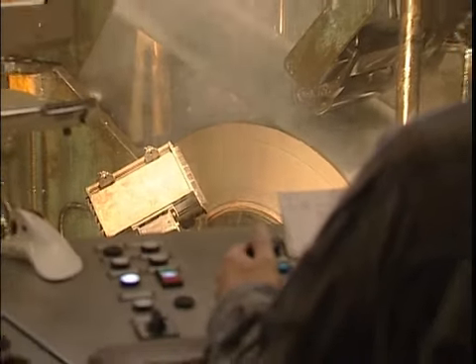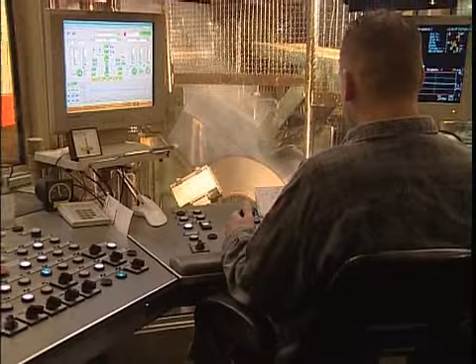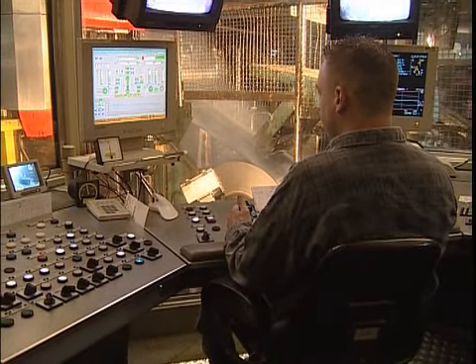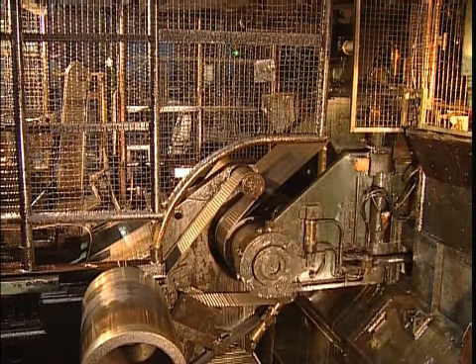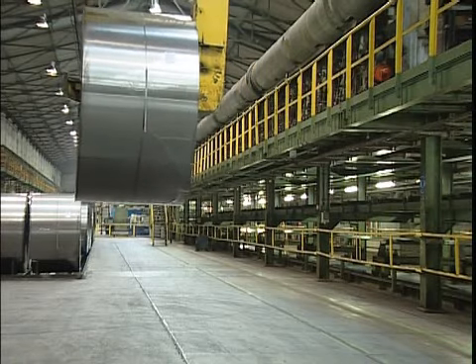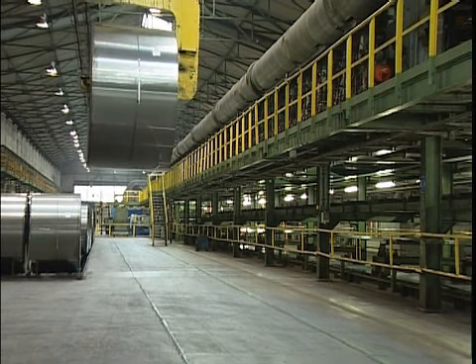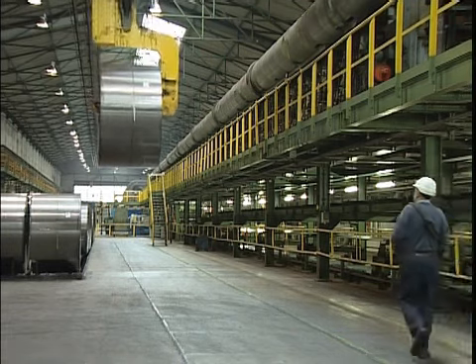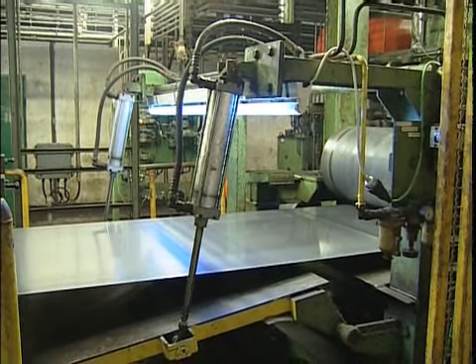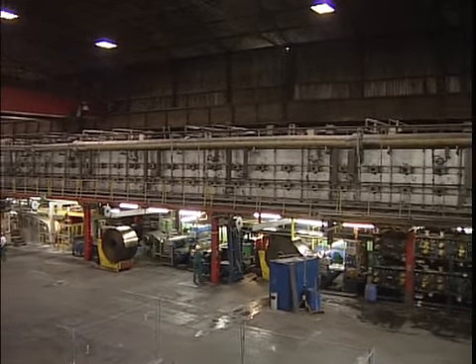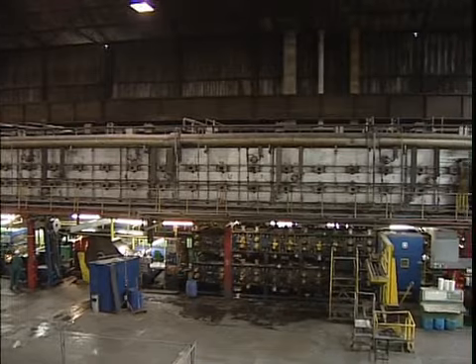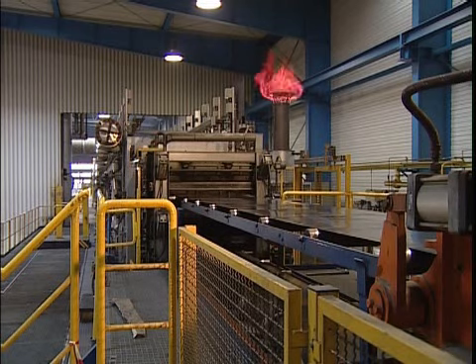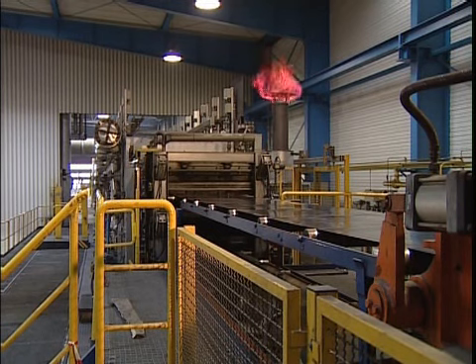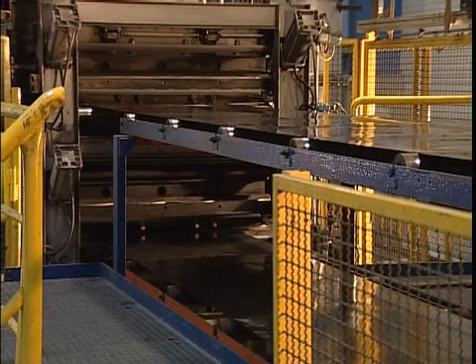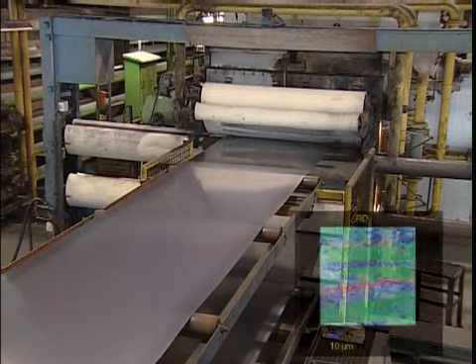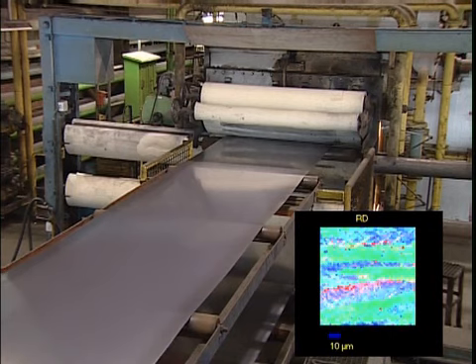The ergonomic optimized conception of the control station, with its numerous CRT displays, is the result of the successful teamwork of the employees involved. Before the final cold rolling of Power Core C, there is an intermediate annealing for the purpose of recrystallization. A decarburization annealing, to avoid magnetic aging, reduces the carbon content under a protective atmosphere of nitrogen, hydrogen and water vapor. A primary recrystallization of the deformed iron into non-oriented crystals 10 micrometers in size starts the process of texture forming.